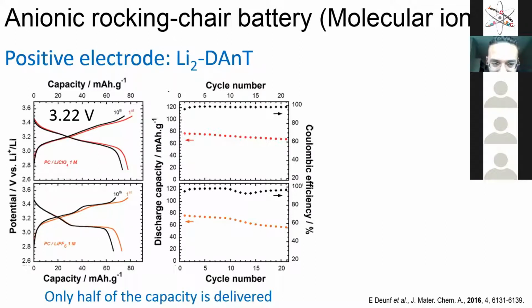I mean, practically, if you want to reach the second electron, you need to go higher in voltage, and if you do this, you will form another molecule which is highly soluble in the electrolyte, and then you will lose the stability. So in order to have good stability, you limit to one electron, and then you provide only 75 milliampere hour per gram, but it is stable, as you can see on the right graph here.